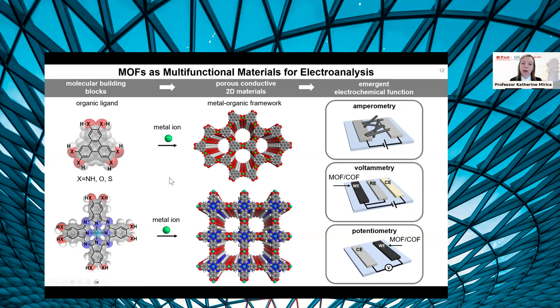So today my talk will focus primarily on using these materials in a chemiresistive device architecture where we're going to measure the output of the device using amperometry, so changes in current. But we also have demonstrated the ability to use these conductive metal organic frameworks as working electrodes in voltammetry for the detection of neurochemicals, for example, redox active analytes. And also in some of our other work, we've demonstrated the ability to use these materials as ion to electron transducers in potentiometry and enable detection of ions. So the point here is that depending on what kind of device architecture we place these materials into, we can get a very different readout from these materials, enabling multifunctionality.